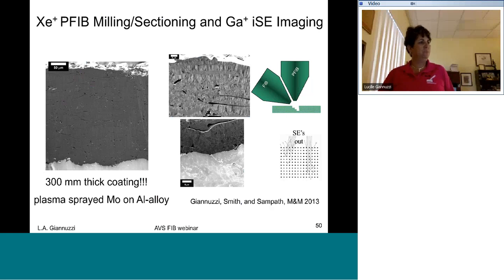Okay, this is a xenon plasma FIB section, and then imaged with the gallium beam. You can see differences in material contrast. Note the very thick coating that you're able to FIB mill through with the xenon plasma FIB, the columnar structure here in this plasma spray coating, and again, the differences in material contrast as well as the differences in grain sizes.